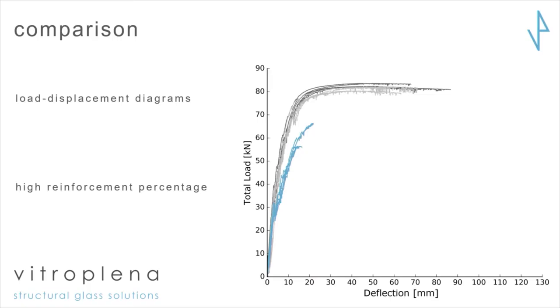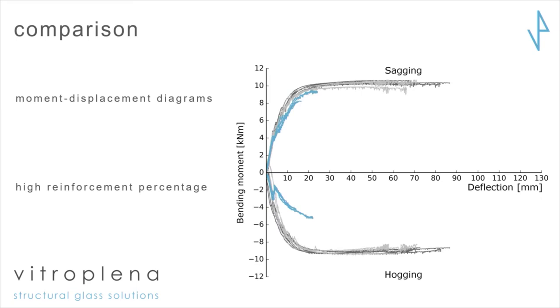The same we can say about the solid or high reinforcement percentage. There, SentryGlas was able to make the reinforcement yield — we had enough stiffness and shear strength of the interlayer. Our cast resin did not. But we see the same effect again when you look at the bending moment.